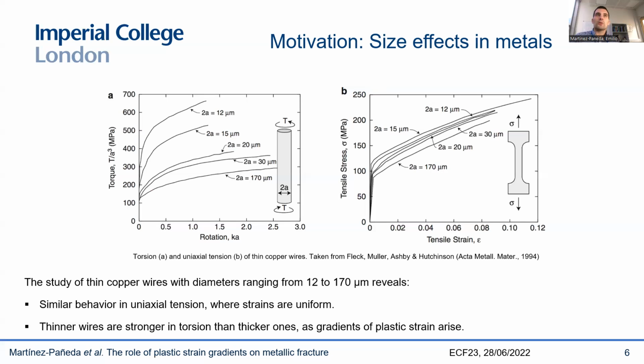And this is important because if I try to simulate these results using conventional continuum theories, for example, using von Mises plasticity, then I wouldn't be able to capture this phenomena. I will basically predict that all the curves fall on top of each other, as we see in the uniaxial tension case, but I wouldn't be able to capture this elevation of strength. So that is the bad news. Conventional continuum theories are not able to capture this role of GNDs and plastic strain gradients because they have no length scale in their constitutive equations.